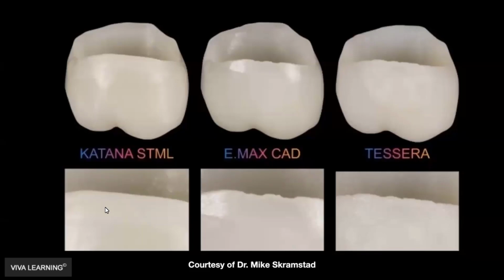When you start getting into the glass ceramics, it is a grinding consistency. We have diamond burrs that are grinding this material away, and it's grinding it away at the exact same size as the material needs to be. What this can often lead to is some chipping, very microscopic chipping at the margin. But if we want a crown that's cemented and sealed to the utmost ability, I would rather mill a zirconia crown than have the Tesseras or the Emaxes or the Empresses or any of the glass ceramic, feldspathic porcelain have this microscopic chipping.